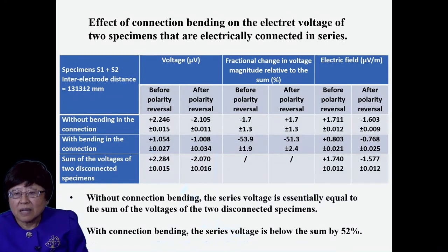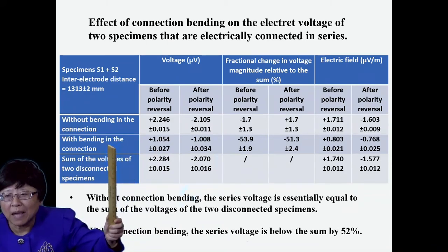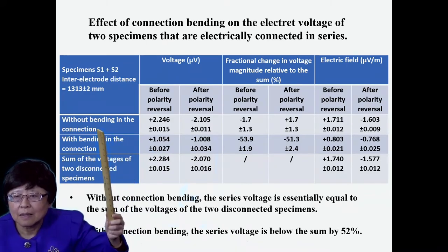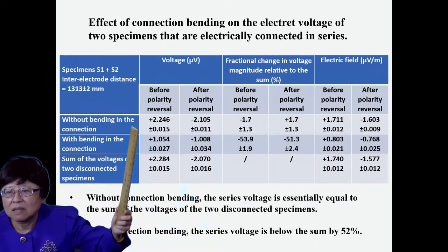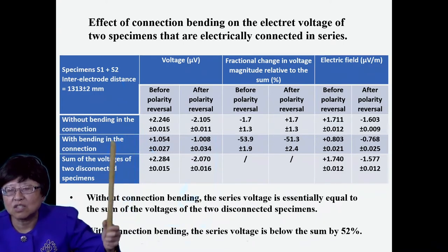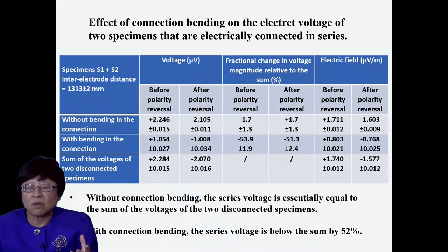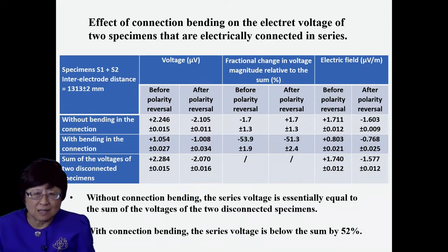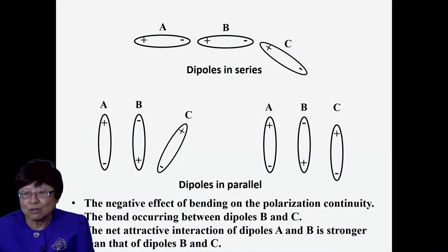As shown here, when you have no bending in the connection, the voltage you get, the series voltage, is just the sum of the two. But if you have bending, then it's roughly 50% of the sum. So half bending is not as good. You get about half of the sum.